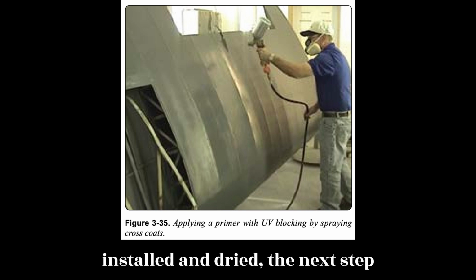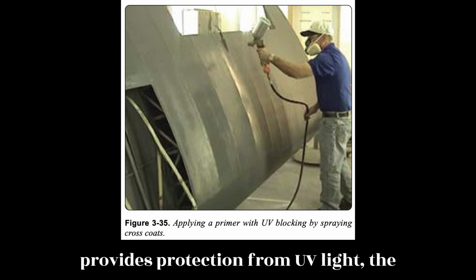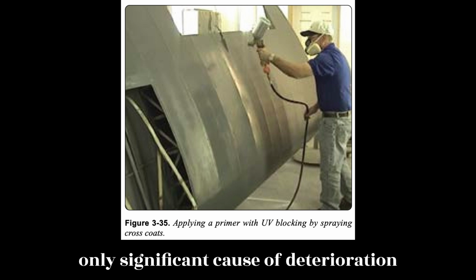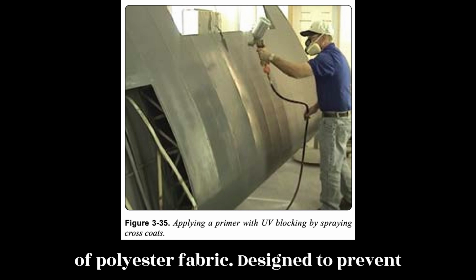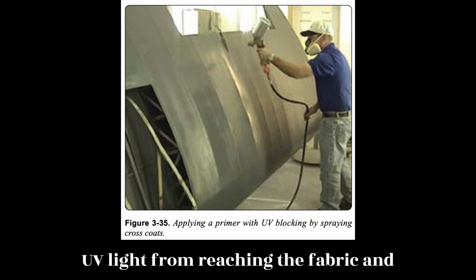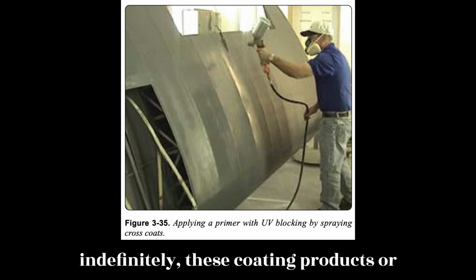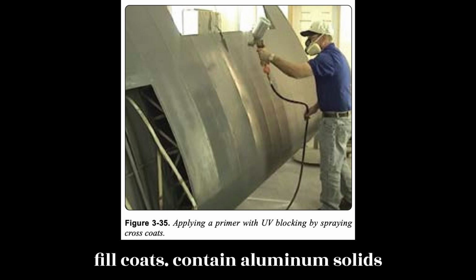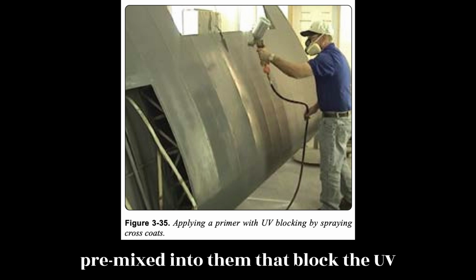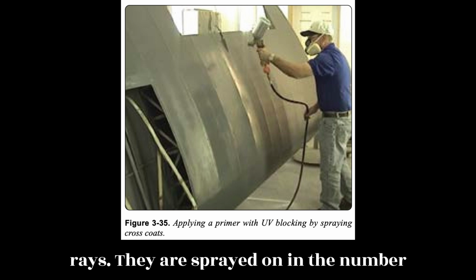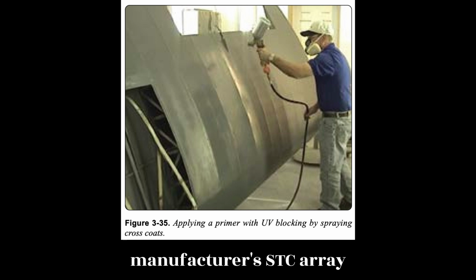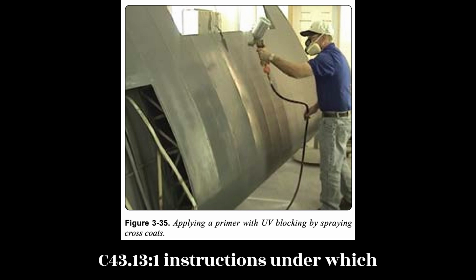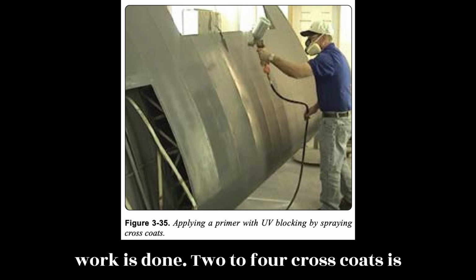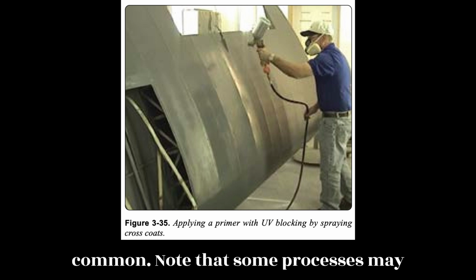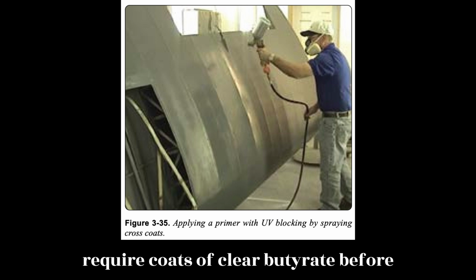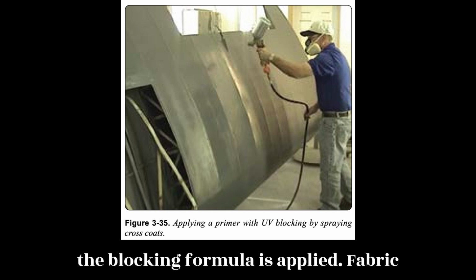With the sealer coats installed and dried, the next step provides protection from UV light, the only significant cause of deterioration of polyester fabric. Designed to prevent UV light from reaching the fabric and extend the life of the fabric indefinitely, these coating products, or fill coats, contain aluminum solids pre-mixed into them that block the UV rays. They are sprayed on in the number of crosscoats as specified in the manufacturer's STC or AC 43.13-1 instructions under which work is done. 2 to 4 crosscoats is common. Note that some processes may require coats of clear butyrate before the blocking formula is applied.